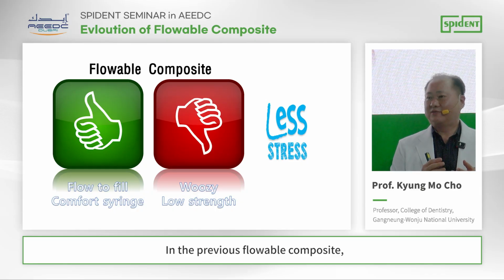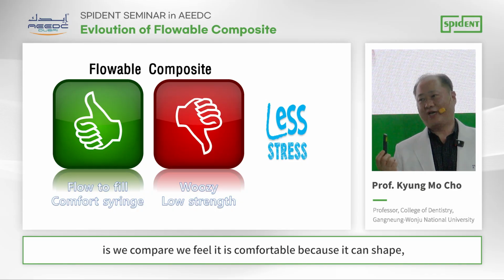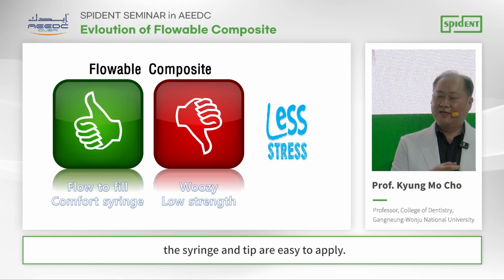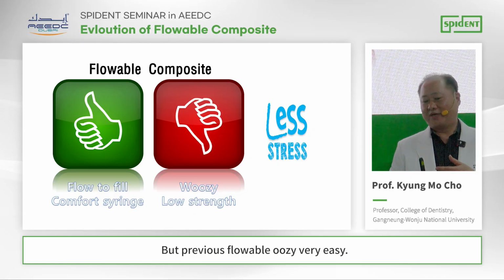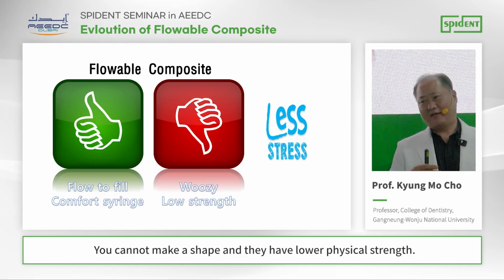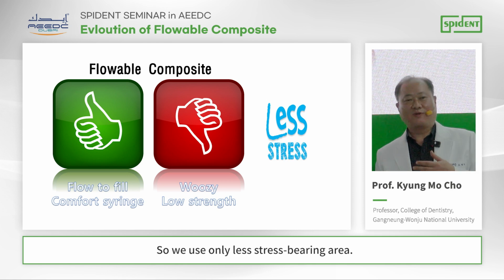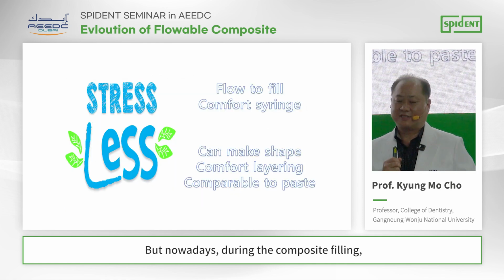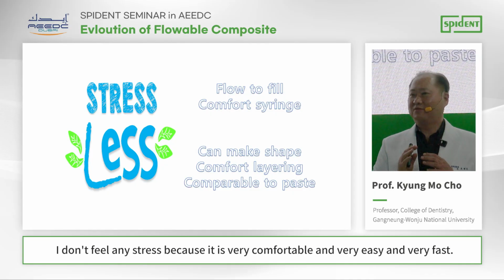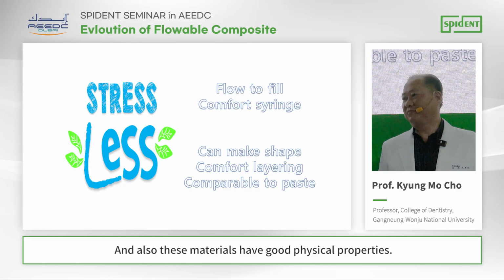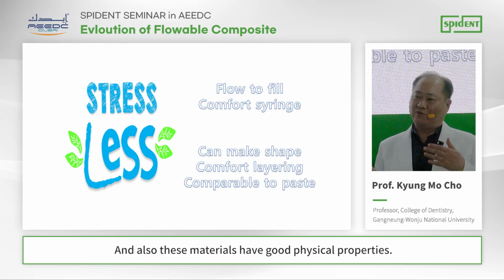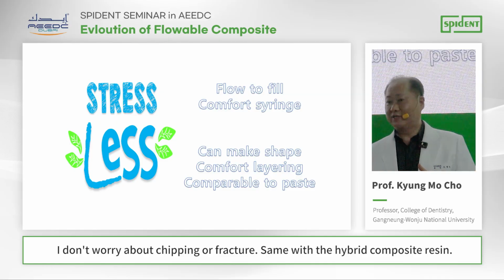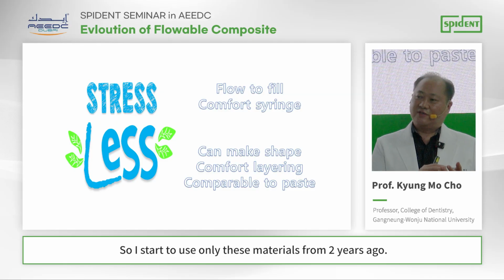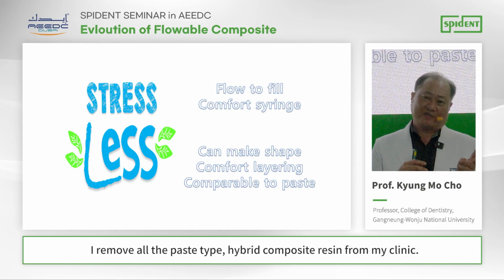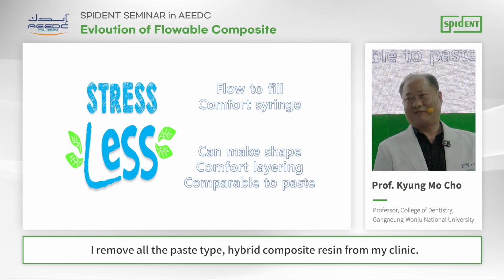With the previous flowable composites, we felt it was comfortable because the shape is a syringe and very easy to apply. But previous flowables ooze easily, so you can't make a shape, and they have lower physical strength. So we used them only in less stress-bearing areas. But nowadays, during composite filling, I don't feel any stress because it's very comfortable, very easy, and very fast. And also, these materials have very good physical properties. I don't worry about chipping or fracture. Same as the hybrid composite. So I started to use only this material from 2 years ago. I removed all the paste type hybrid composite from my clinic.